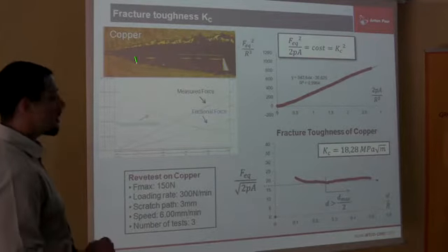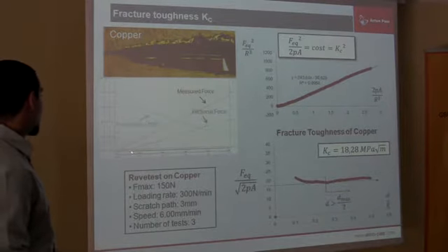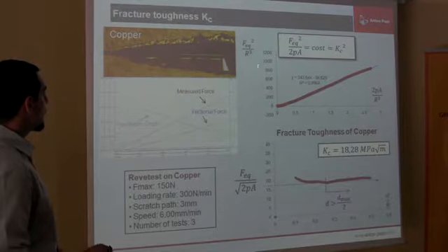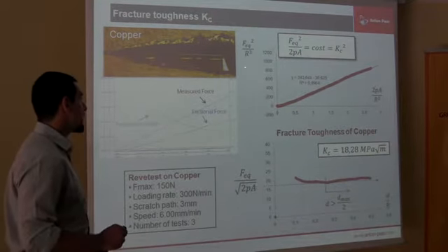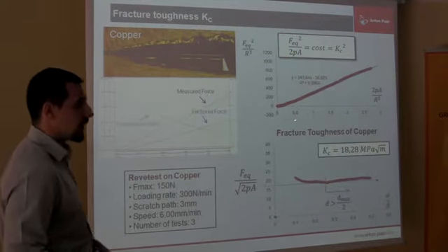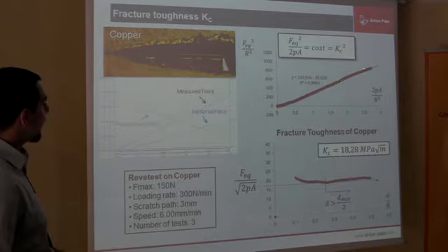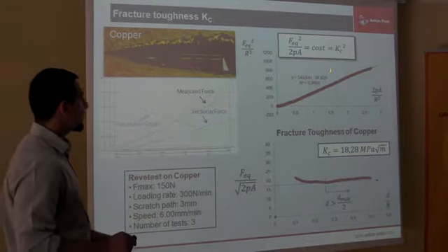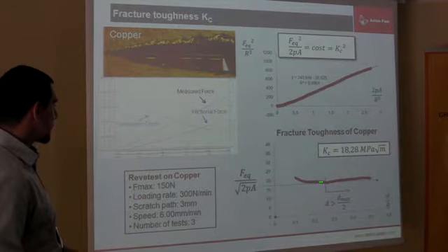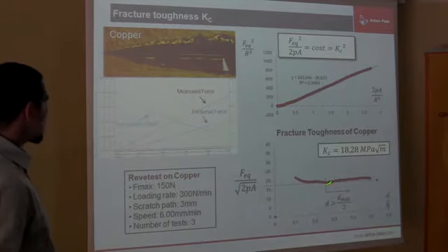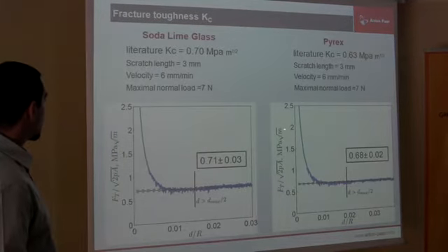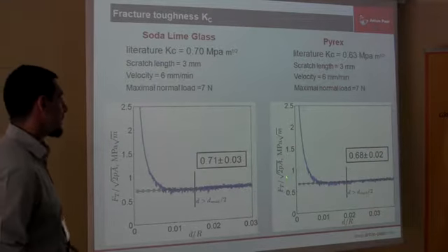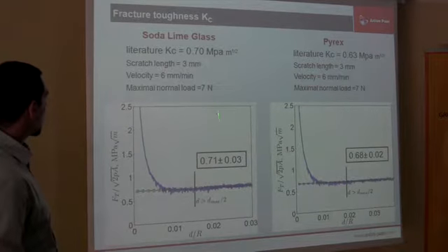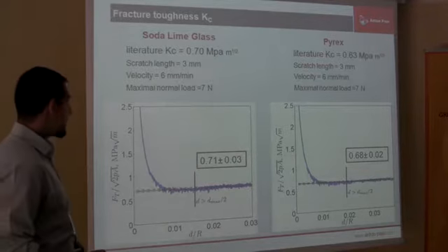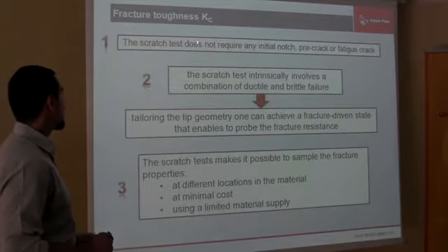Then we do another scratch in copper, and also here we record the applied force, the penetration depth and the frictional force. Then we plot the force over the radius of the tip against the shape of our indentation shape, and we found a linear correlation that is proportional to the fracture toughness. So we can extract the fracture toughness, and we found a value very close to the known one, and this is for the copper. Professor Hulme also found the same results with soda lime glass and Pyrex. These results are in very good agreement with literature. So this is a way to evaluate fracture toughness.